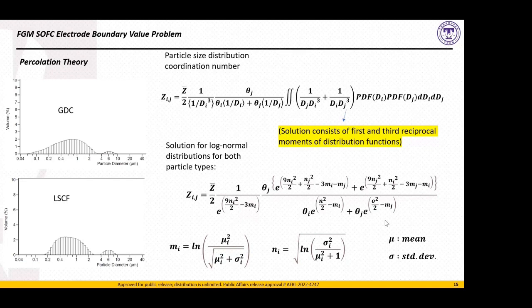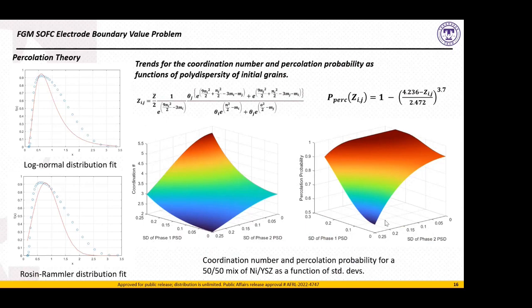So this defines their coordination number, basically the ability of a particle of one phase to contact a particle of another phase or another particle within its own phase type. See here the maps and the trends for the coordination number and the percolation probability as a function of the polydispersity of the grains. And so you can see here that for phase one to be able to contact and percolate, form a percolating network with phase two, that decreases as you decrease the standard deviation of phase one and increase the standard deviation of phase two. So you end up having particles of one phase that end up blocking out the particle of the opposite phase.